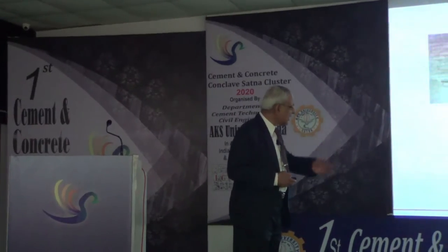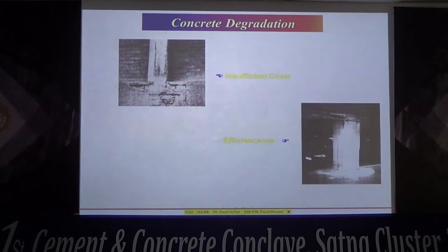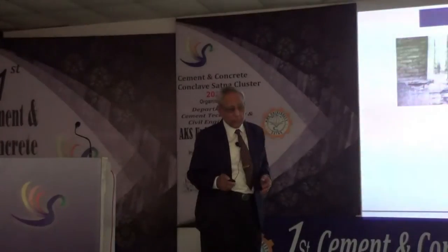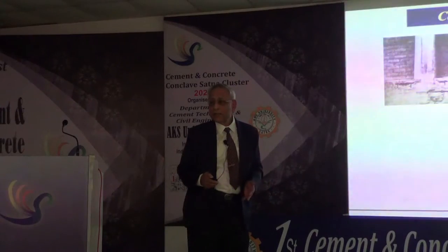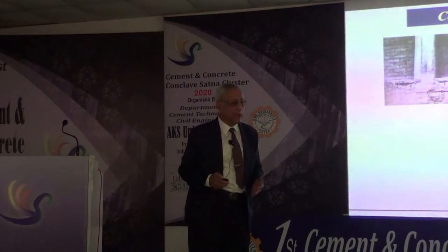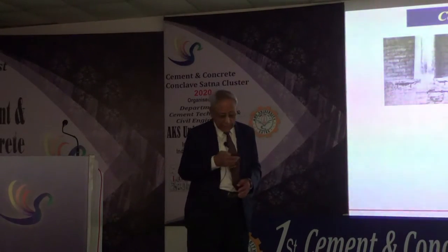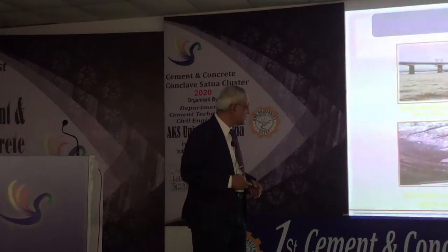Basically, the cover concrete, as I have said, effloresces, as you would have seen in many buildings, particularly in earlier years when OPC was the prime binder. These days efflorescence is much less because we are using blended cements more, but even there you would see white streaks around the building, which is due to the calcium salts being leached out. So therefore, there is an efflorescence effect.